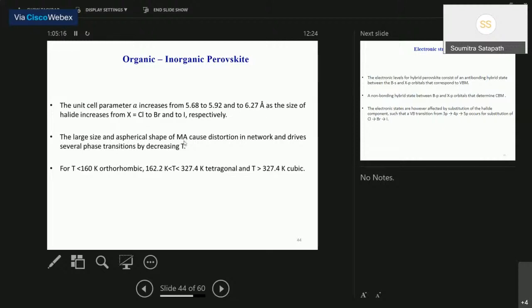Similarly, as I mentioned, this organic cation introduces rotational distortion in the network, and that drives several phase transitions. Now, this shows a temperature-dependent phase transition. At room temperature, it shows a tetragonal crystal phase. But at low temperature, if you cool down the perovskite below 160 Kelvin, it shows an orthorhombic crystal phase. And at high temperature, greater than 327 Kelvin, it converts to a more symmetric cubic phase. So it shows temperature-dependent crystal symmetry. And since the crystal symmetry is different depending upon the temperature, its optical and electronic properties also change depending on the temperature.